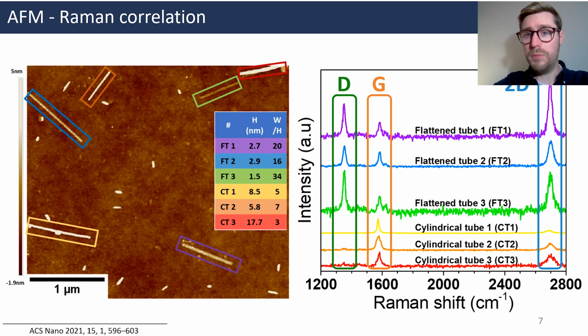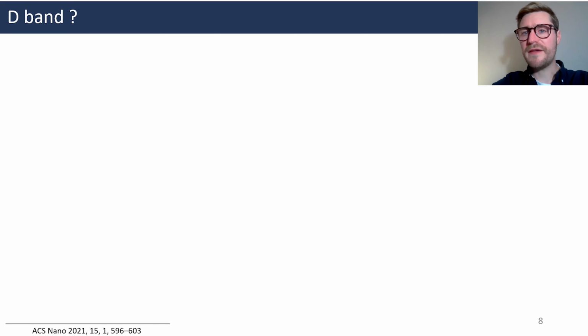In fact, both cylindrical and flattened tubes come from the same solution. They undergo the exact same chemical and physical treatment. As a result, all objects are expected to present the same structural defect density. But then, if this band present only on flattened tubes is not induced by structural defects, where is it coming from? We first verified that this band can be called a D-band.